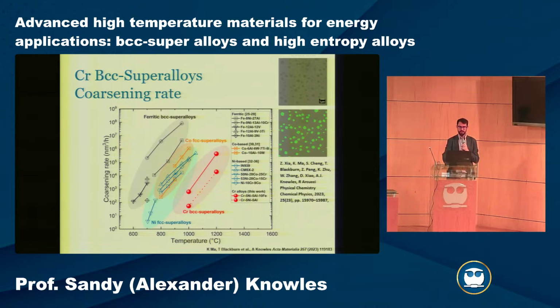So what we found is, in comparison to, say, ferritic superalloys, nickel-based superalloys, or cobalt-based superalloys, this new material of chromium superalloys has a much slower coarsening rate of the precipitates. So at least in terms of microstructure stability, we've got a big advantage there.